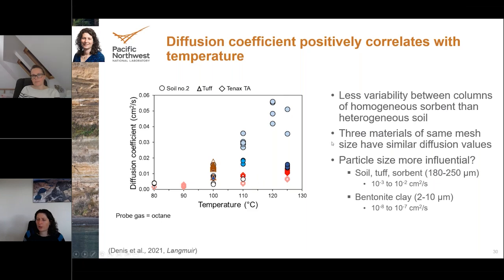And then also, at least in this case, the 3 materials which have the same particle size or the same mesh size, they all had in the ballpark of similar diffusion values. It was hard to distinguish between the materials. But then we had a bentonite clay, which happened to be a much smaller particle size. In that case, I put just the order of magnitude results here for the diffusion coefficient, but we had several order of magnitude decrease in diffusion coefficient that was paralleled with the smaller particle size.